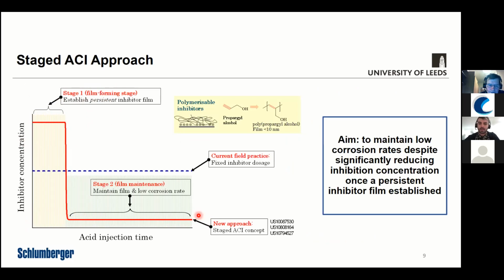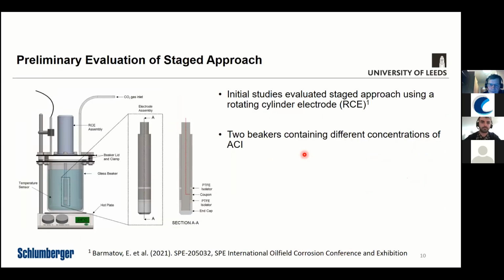So the idea being that a lower concentration of inhibitor is required to maintain the polymerization process once the film has been established on the surface. And then ideally that would give you a low corrosion rate, or no change in corrosion rate, compared to using a high concentration. So this technique's patented by Schlumberger, and their aim is to take this approach and optimize it to change how we protect carbon steel in these environments by varying the dose to achieve the optimum conditions.